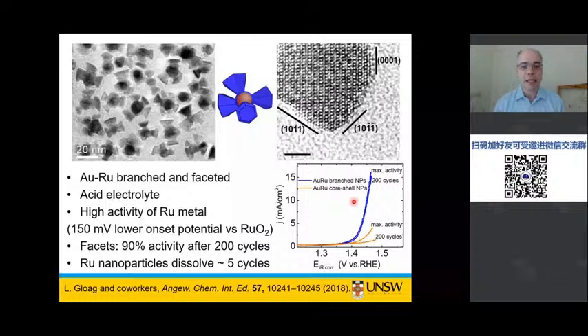So even after 200 cycles, we still have about 90% of the maximum activity that we achieved. For us, this was a tremendous result because, as I said, for all the other examples of ruthenium nanoparticles for OER, they would always just dissolve up into the electrolyte after about 5 cycles. They're all completely gone. So this was the first time there was really an illustration that you could make ruthenium metal-based nanoparticles that could have some stability for oxygen evolution reaction.